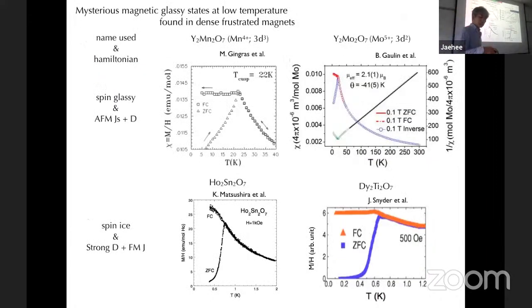All right. Now this glassiness, in fact, the freezing phenomena, appeared in very different systems of frustrated magnets, for instance. There are various systems, for instance, manganese, molybdenum, and all these pyrochlore systems, and holmium and dysprosium, and their Hamiltonians are very different. So manganese and molybdenum, their Hamiltonian has dominant antiferromagnetic exchange interactions and a weaker single-ion anisotropy.